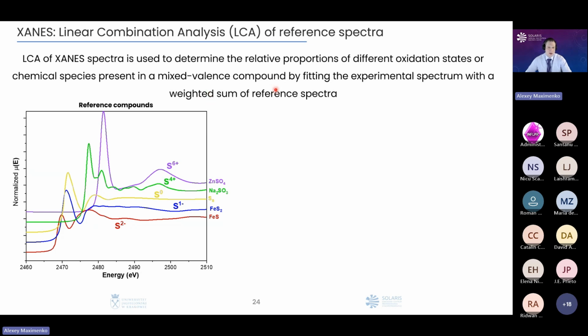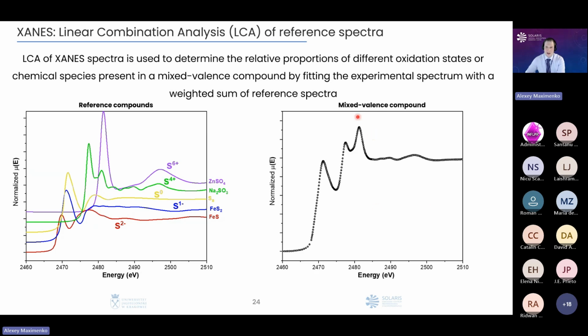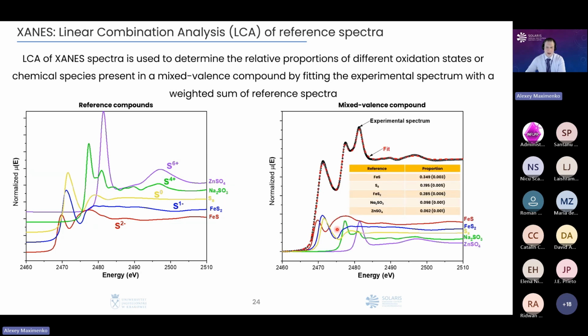In order to do this, you measure reference samples whose composition you know very well. For example, here are the different compounds which I bought and measured, their spectra. And then, for example, I measured a mixed valence compound, which was actually a mixture of all of these phases. And then I make a linear combination fitting, and it was then easy for me to understand how much of the atoms, for example, here I measured sulfur.